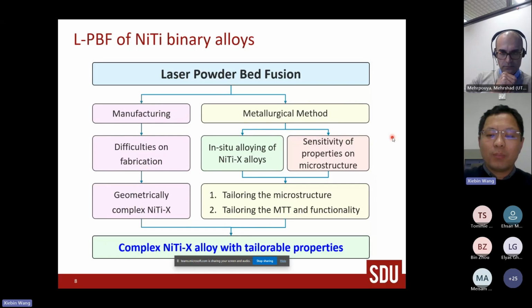Because the transformation behavior of nickel titanium alloys is very sensitive to its microstructure, if you change the LPBF process, you will more or less modify the microstructure. Based on this relation, we could tailor, or at least change, the transformation behavior of these alloys. I will show the examples later. And if we achieve all this, we may have the approaches to make complex nickel titanium based structures with tailorable properties.